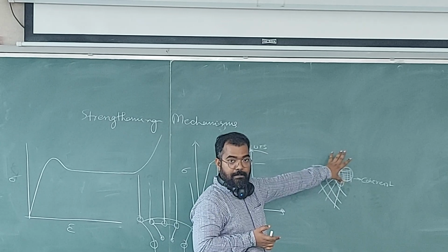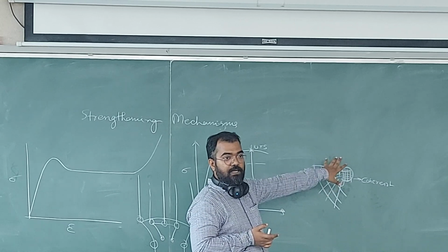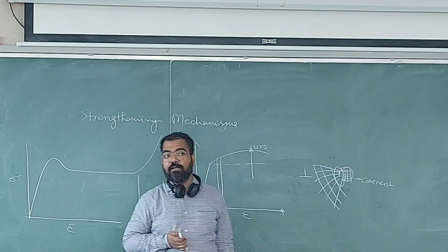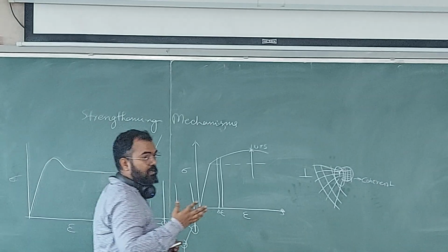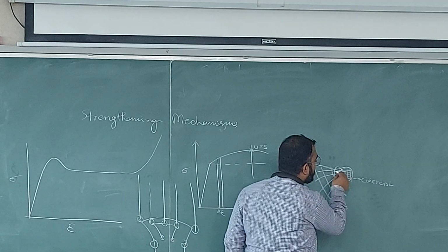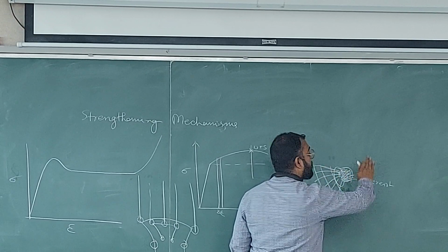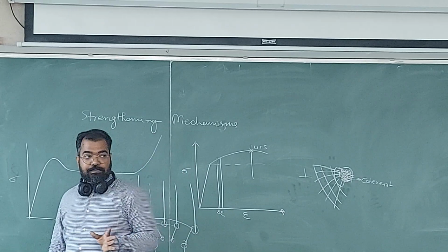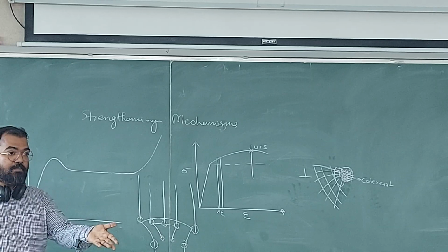This is not happening abruptly. Okay, so you will have a lot of dislocations arising at the interface of the precipitate when it becomes semi-coherent, and the end point of a precipitate is an incoherent precipitate. When you have no continuation from the matrix to the precipitate, so you really have no continuation. So this forms a different crystal structure altogether. So now it's a different crystal structure. Matrix is a different crystal structure. There is no coherence. Okay. So there is a clear interface there. So now there is a boundary where dislocation will pile up and will not be able to go.